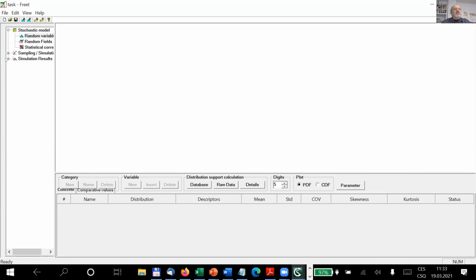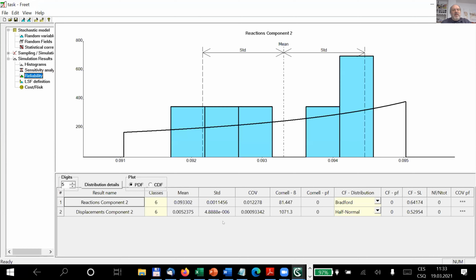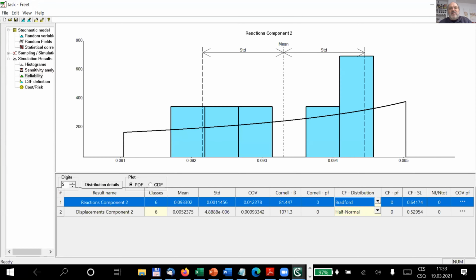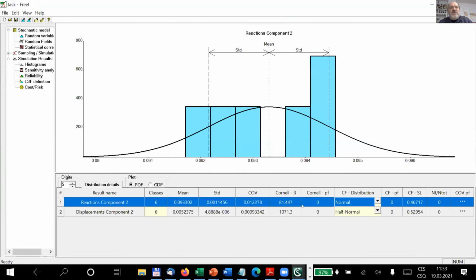So we go to the results, we go directly to the reliability, and we can set the normal distribution, which looks like this. So our mean value is again 93, before it was 94, but the range is now only from 90 to about 96. So we are in a more narrow band.